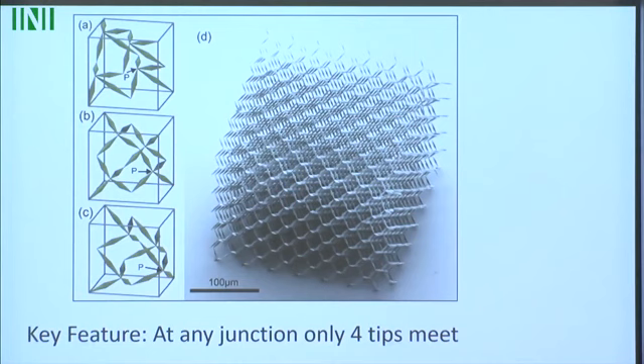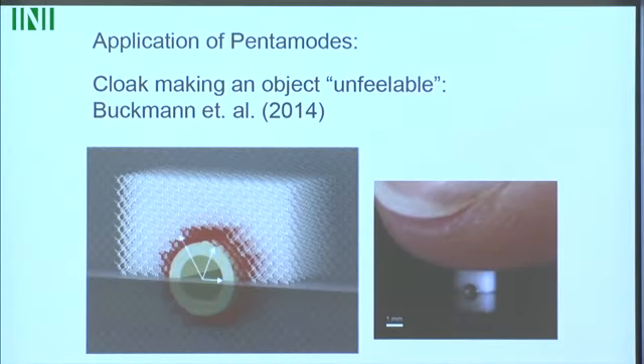The key thing about this structure is that at any junction, only 4 tips meet. So if you have a tension in this, then by balance of forces, that determines uniquely the tension in the 3 neighboring double cone elements. If you apply that at every point in the structure, basically if you know the tension in one of these, you know the tension throughout the structure, and you know the stress throughout the structure as well. One application of this was making a sort of unfeelability cloak, where they took this pentamode structure and a pentamode structure with a slightly smaller bulk modulus, and used it to hide a rigid inclusion.